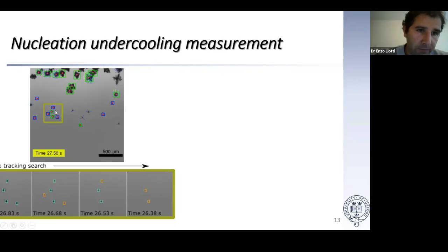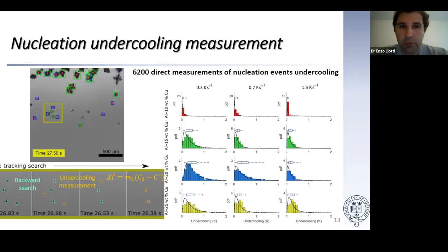So the algorithm was finding, for example, if we take this little square here, it was actually detecting these 5 grains and then going backwards in time and essentially trying to search for the first frame in which, in that specific location where the grain formed, the grain was not yet formed. And then by measuring the solute concentration at that specific point, this value called undercooling could be measured. And by doing this, the algorithm was able to detect and measure 6,200 nucleation events. And again, this is the first time that in metallurgy we can measure nucleation undercooling directly for each individual grain and not as an overall value.